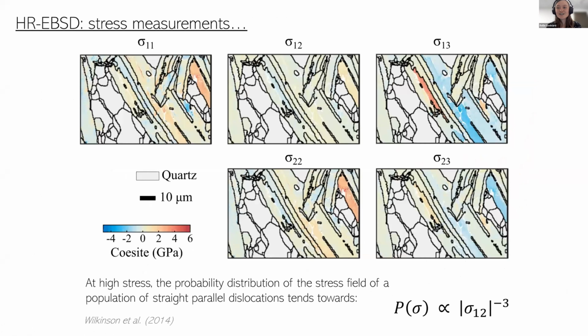2 minutes. So we wanted to look, okay, I'm nearly finished. So we wanted to look at the stresses that were felt by these coesites and quantify that a little bit more, which is what we plot up here. These are internal stresses. You can see that we're getting GPa level stresses on the grain scale. We've got quartz in the gray, and then the nice colorful things of the coesite. So we're seeing a lot of internal stress heterogeneity in that sample.